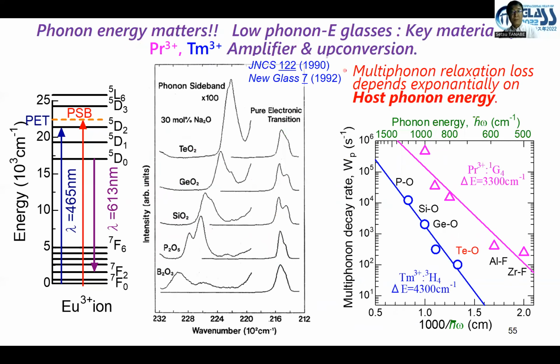And utilizing low phonon energy glass is necessary because the initial level of the 1.3 micron or 1.4 micron luminescence in praseodymium or thulium has a very narrow energy gap to the next lower level. And this is the dependence of the multiphonon decay rate as a function of inverse phonon energy, following the Miyakawa-Dexter law. So praseodymium suffers from high multiphonon relaxation. Compared with that, thulium has less because of a little bit larger energy gap to the next lower level. Instead, the slope becomes a little bit steeper.